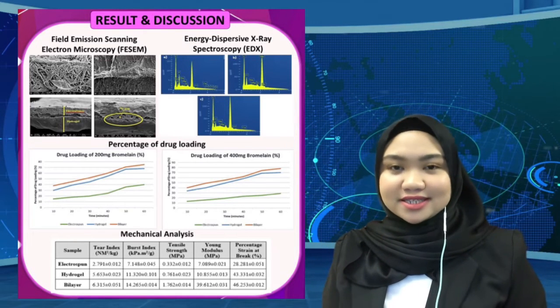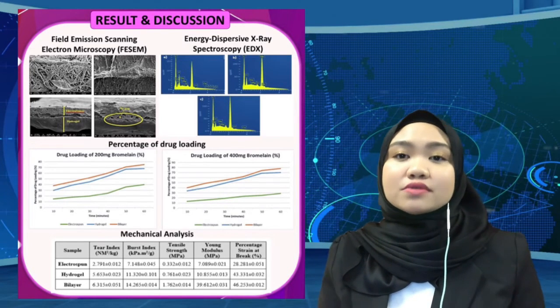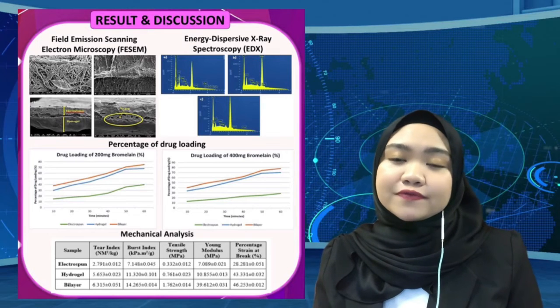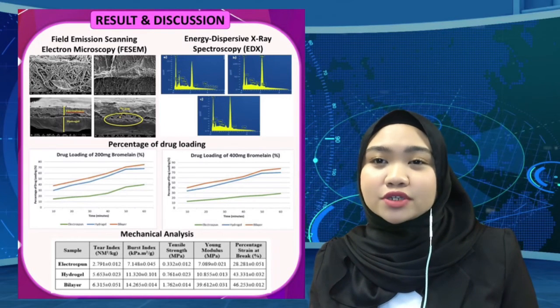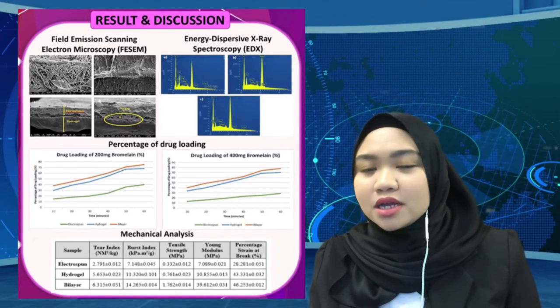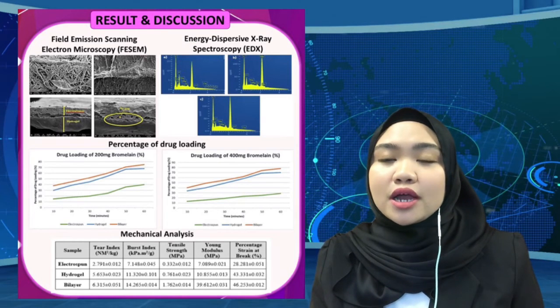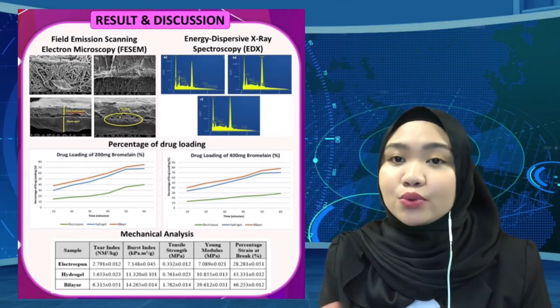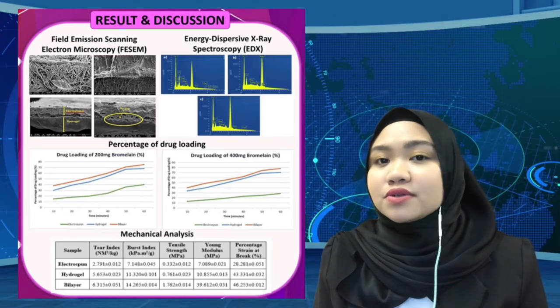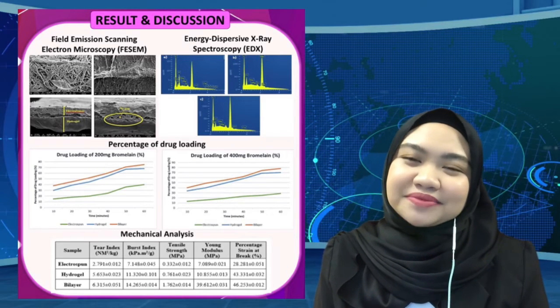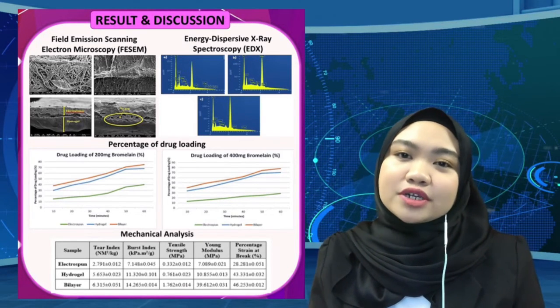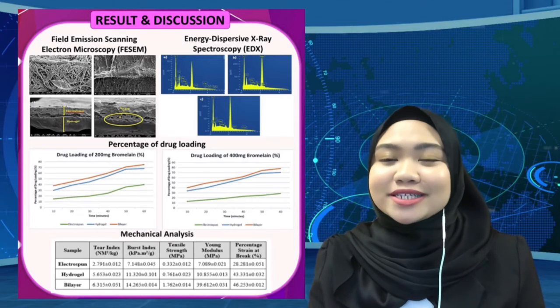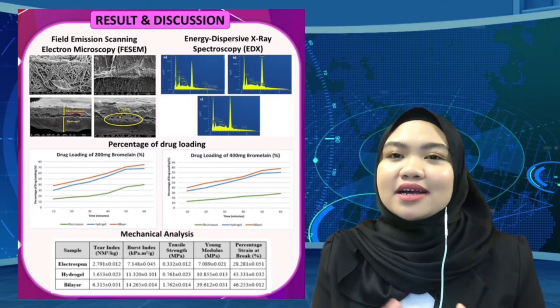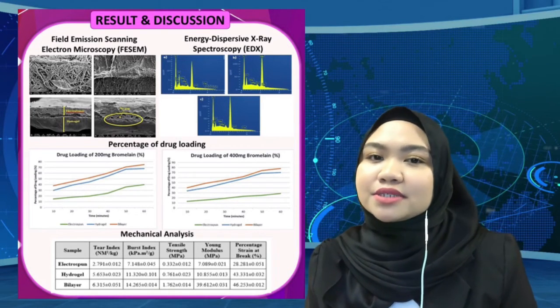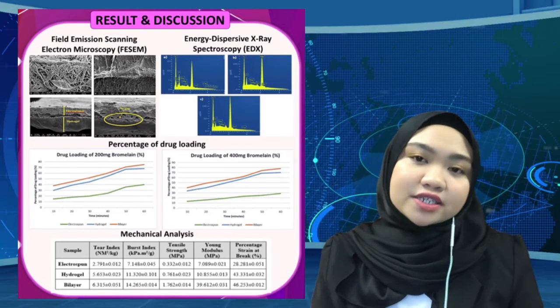So the last one is drug loading. It was observed that electrospun achieved a lower percentage of drug loading in both concentrations of bromelain. Due to the structure of electrospun mentioned above as discrete and one-layer composite, a lower absorption ability of the drug was obtained. This is followed by hydrogel, which has a high percentage of drug loading, which is 68% for 200 mg and 70% for 400 mg.